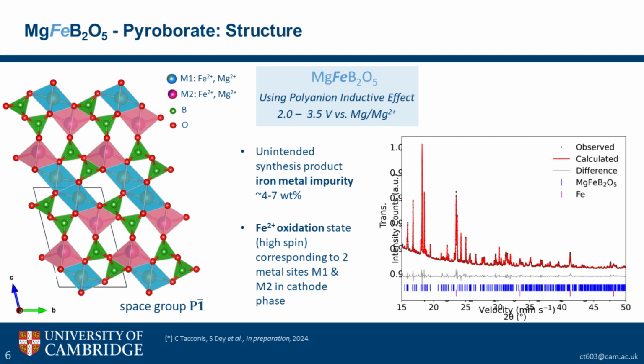And these polyanion materials are characterized by these sort of 2 metal sites, M1 in blue and M2, which form these ribbons that extend in the A-axis 2-dimensionally. And they have 2 slightly different chemical environments and are occupied by a disordered occupation of magnesium and iron.